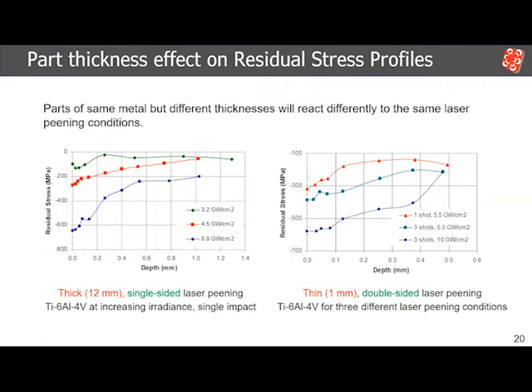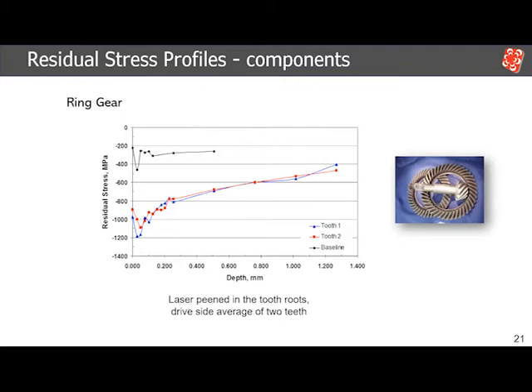Our modeling capabilities are supported by the large library of residual stress data that we have for different peening processes on different materials with different thicknesses and different geometries. So we have a large material database that our models can use to build, verify, and verify again until we reach a model that we're happy with. Then we can apply that specific model to a complicated geometry, which helps us optimize our laser peening process. After that comes experimental verification of the results that were generated by the model. So we do actual residual stress measurement to verify the simulation results.